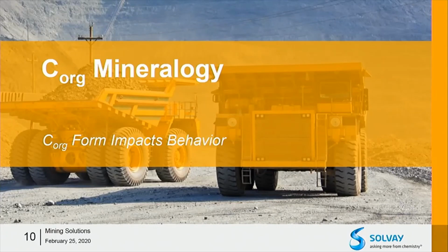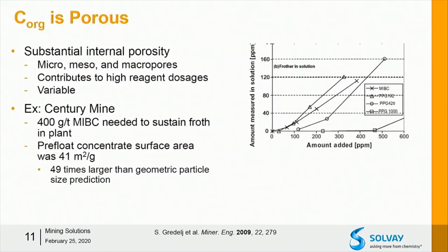Okay, so here are the most important concepts around carbon as a material and the mineralogy that are really important to understand how it impacts the flotation of sulfide ores. Okay, so the first is that carbon is a naturally porous material. Micro, meso, and macro porosity tends to be seen across a range of different carbon samples. And because of that, you tend to see very high reagent dosages. Just an example from Century Mine, the pre-flotation concentrate had a surface area that was 50 times larger than what you would expect just based on its geometric particle size.